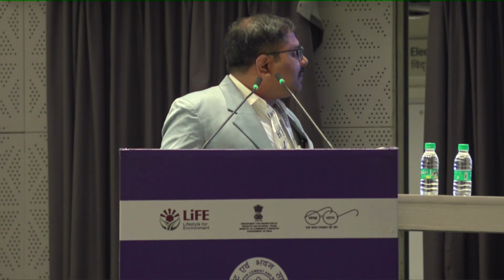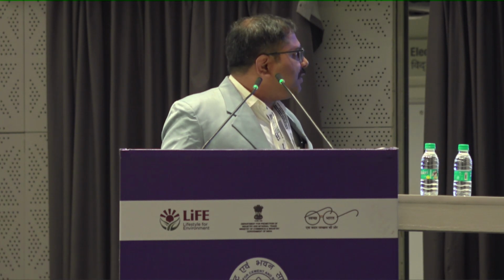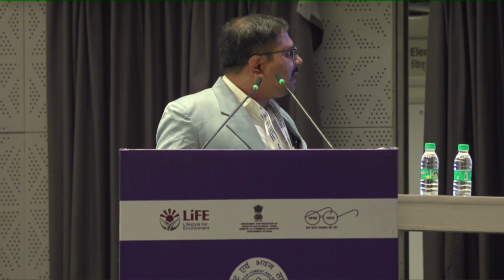The composition of the LC3 was 15% limestone, 30% calcined clay, 50% clinker, and the remainder was gypsum. We have separately ground the calcined clay and mixed it with ground clinker, limestone, and gypsum. Similarly, PPC has been prepared by mixing fly ash with ground clinker and gypsum. The lime reactivity of calcined clay was more than 8 MPa.